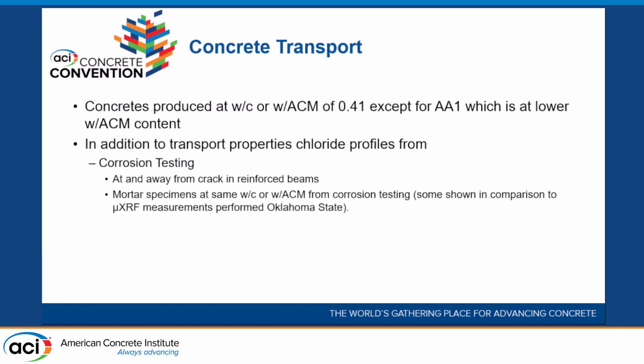All the concretes in the study were produced at a water to cement ratio of 0.41, except A1, which required a lower amount. We measured transport properties for the chloride, and we also measured them after corrosion testing. So we actually measured the chloride contents in the actual concrete that was under corrosion testing. We also did some comparisons with some of our mortar samples, where we did normal titrations, and they compared extremely well with the micro X-ray experiments at Oklahoma State.